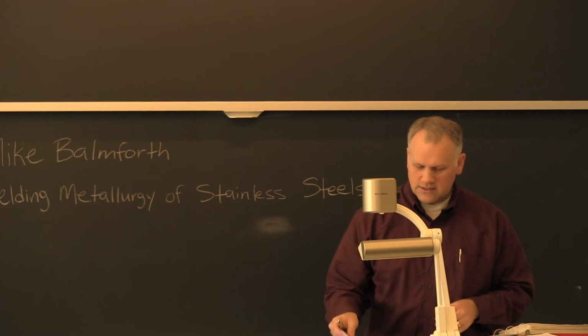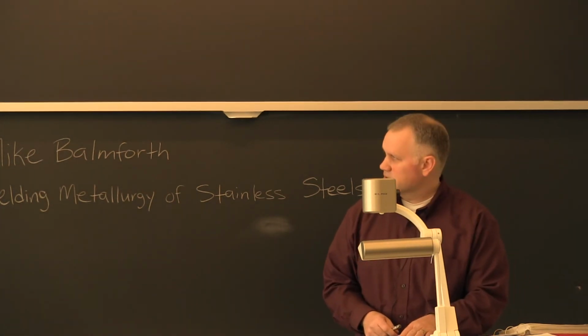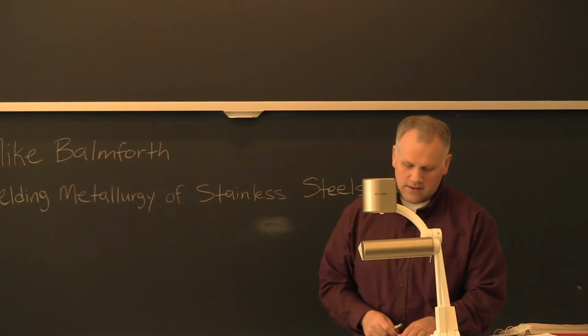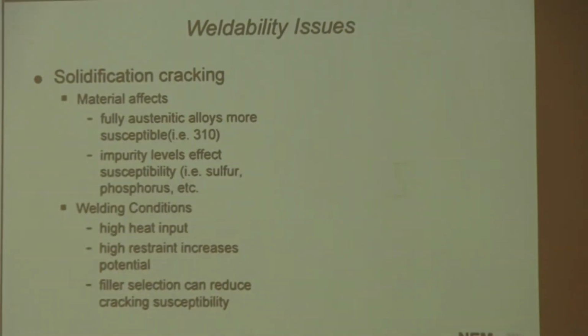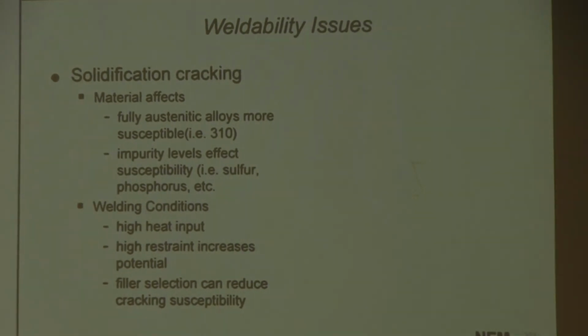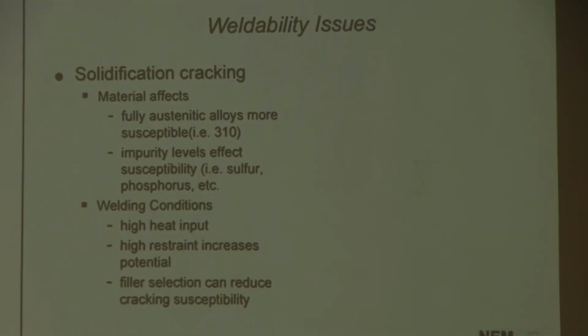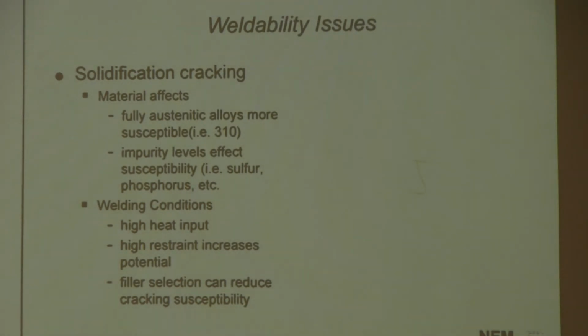So next I wanted to talk about some of the issues that can arise when you're welding on stainless steels, and probably the biggest issue that you need to be aware of when you're welding on austenitic stainless steels is solidification cracking, which is basically cracks that form in the material after you've welded on it as it's re-solidifying. And what you find is that the fully austenitic alloys are more susceptible.